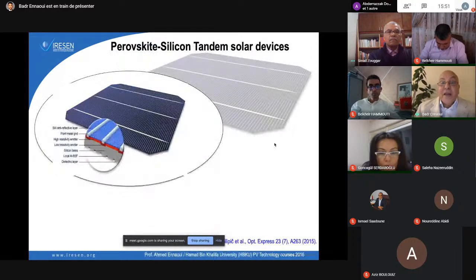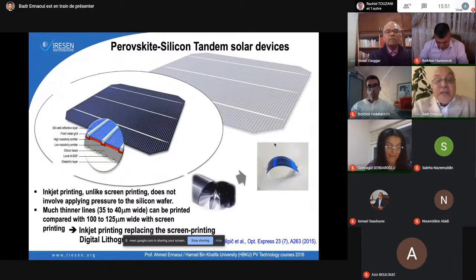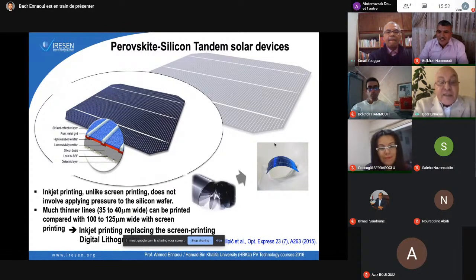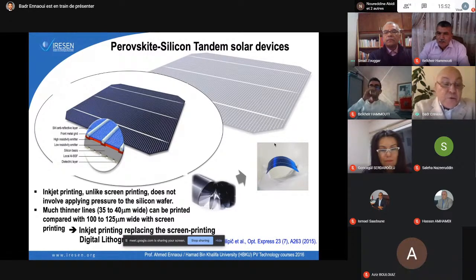Now, for the perovskite silicon tandem device, you can also use inkjet printing. You know that one of the problems is that we are using what we call screen printing to make the contact, what you see here in this figure. You can now make this contact much thinner, and you gain in the active surface of your solar cell, and then you can gain on efficiency. You can make thinner lines, from 35 to 40 micrometers, which you cannot realize with screen printing, for example.